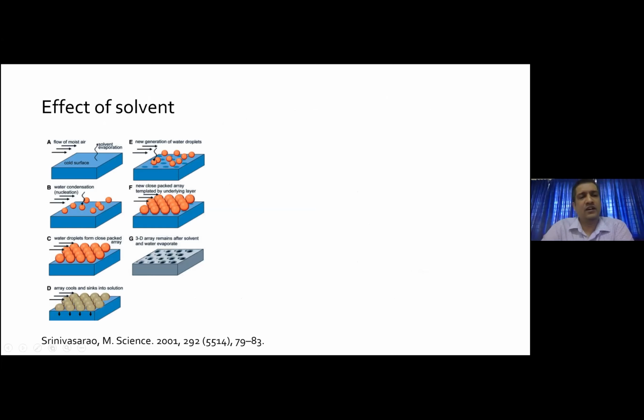So coming to the effect of solvent, the density of solvent is also very important, because most of the time the breath figures are performed on a flat surface where you have, let's say, a thin film onto which the solvent molecule is distributed evenly. When the solvent molecule is heavier than the condensate, most often it is water droplet, if the solvent molecule has higher density compared to the water droplet, the condensation of water droplet pushes the solvent molecule further down, creating very deep or multiple layers of this breath figure pattern formation.